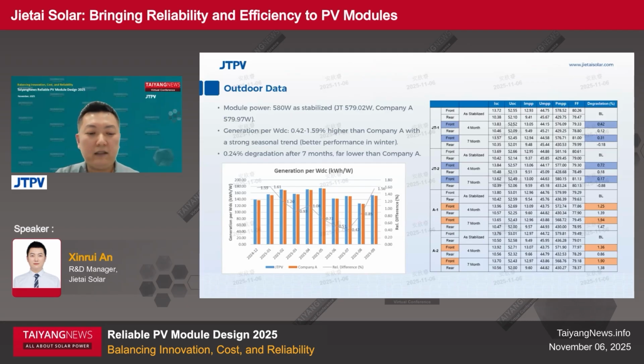This can be explained by the difference in cell performance. As I just mentioned, we have a small sacrifice in Voc for better UV reliability. And we are also very prudent in choosing the silver paste. We avoid paste with excessively low corrosivity, which can increase cell Voc but potentially put DH at risk. As a result, our Voc is lower than company A, leading to a slightly higher temperature coefficient for our module. And the high temperature in summer is more favorable for company A, so it reduces the gap between the two groups.